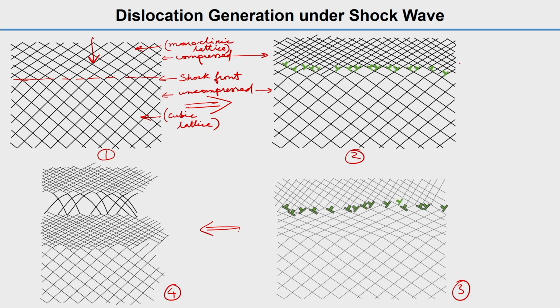So, when the stresses reach above a threshold level, they will generate dislocations. Okay. So, this is the generation of these dislocations. You can see the extra half planes here, and also these extra half planes, here extra half planes. So, the planes are not continuous, these green ones are all edge dislocations you were shown. And this is called a dislocation interface.